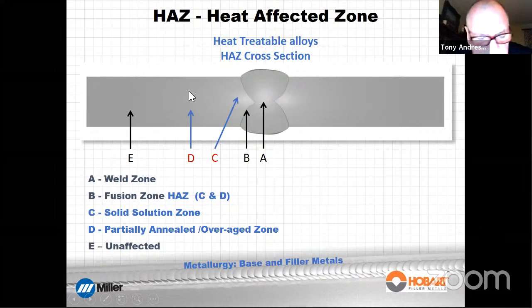The non-heat treatable, it doesn't matter how hot you get them, you always anneal the heat affected zone. The heat treatables, absolutely. The higher you get these, the higher the temperature in the heat affected zone during welding, the lower the strength in the transverse condition. So when people fail welding procedure qualification tests with the 6000 series, right, on their transverse tensile tests, the reason is just about always that they are overheating the base material during the welding process, right?